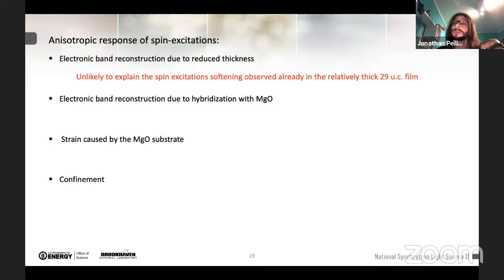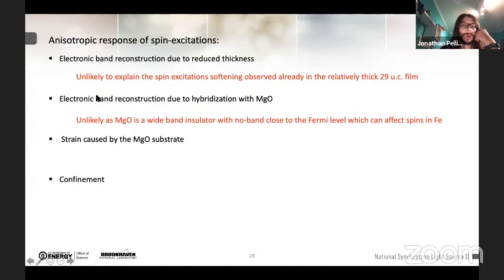The second effect that we thought of was a possible hybridization between the iron bands and the MgO substrate. However, this is unlikely because MgO is a wide-band insulator and it has no bands close to the Fermi level which could hybridize with bands of iron, leading to a reconstruction of the spin excitation dispersion of our film. Another possible reason could be strain. However, we performed a diffraction measurement that showed that 29 unit cell films are already almost fully relaxed.